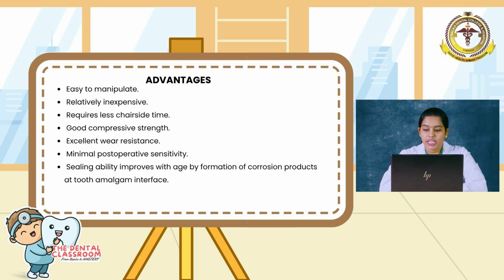It is observed that though corrosion and corrosion products are detrimental to a restoration, it is advantageous in amalgam restoration to a certain extent. Since amalgam does not bond to the tooth, the corrosion products seal the amalgam tooth interface. The self-sealing ability of low copper amalgam is better than that of high copper amalgam, as the rate of corrosion is more in low copper amalgam.